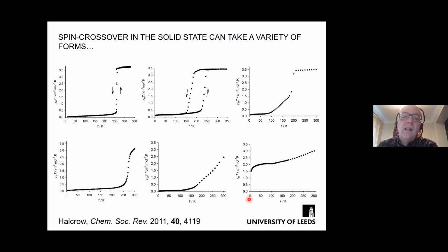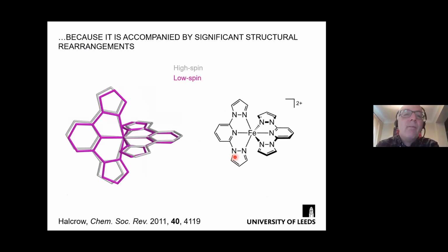And so to understand why this crystal behaves very nicely and this crystal does not, you have to understand the molecules in your crystal and how those molecules interact with each other in the lattice, because both of these factors are important. And they're important basically because the structure of your complex or your iron center changes by a significant amount during the crystal phase change between the high spin and low spin states.